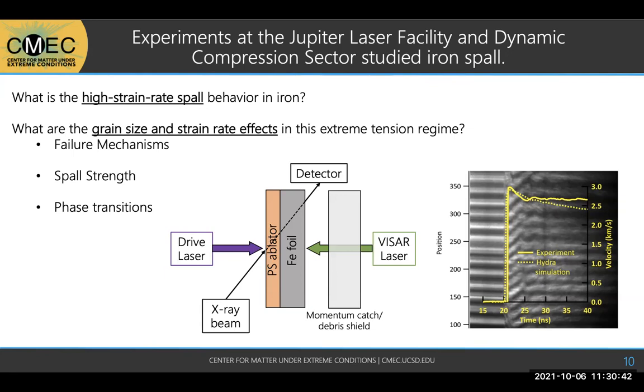Because obviously, as I was mentioning, that VISAR is super important for all of our metrics. And so we actually got a lot of really nice data. And then at the dynamic compression sector, we were able to do the in situ X-ray diffraction, and you can see how that X-ray beam comes in at that angle. But both experiments were designed to probe very similar pressure and strain rate conditions. And so we tried our best to compare apples to apples. Next slide.